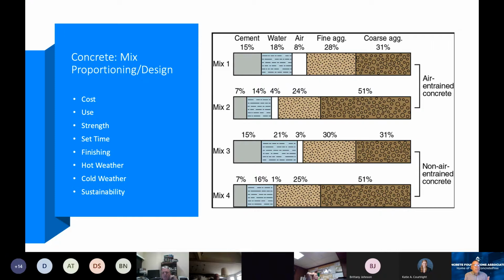And so 14% water in mix 2, let's say we don't add water to it, we're going to consume about 60% of that by hydration. We're going to lose about 40% of it to evaporation. And then depending on how well we control the moisture content, we could see that change either way. So then you could say 100% of my volume, my dimension size, if I consume the 14% or lose it, I suddenly go from 100% to 86%. And that's where we begin to set concrete up for the type of cracking that most often is the callback or the concerning call that we get.